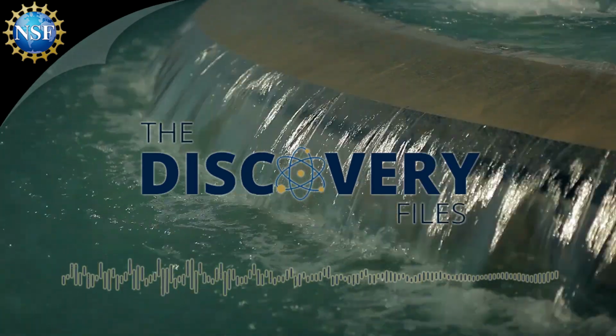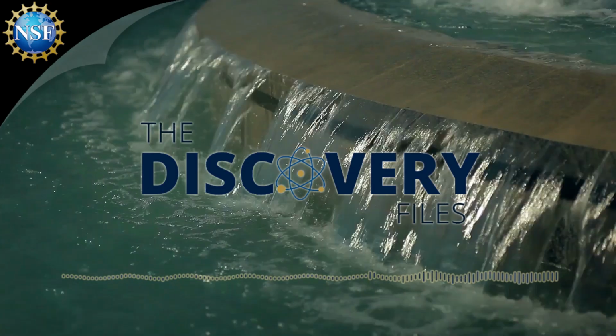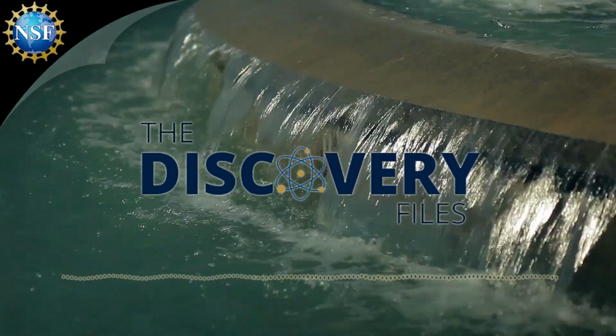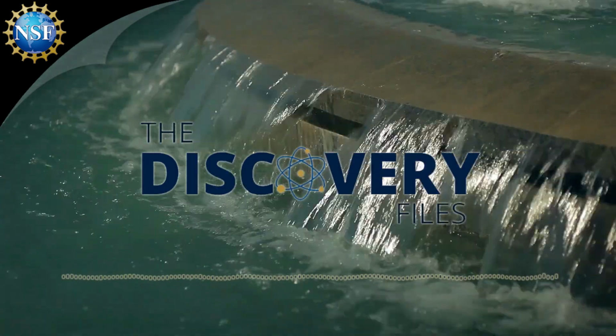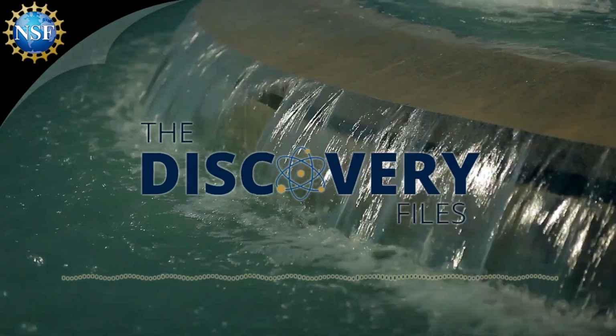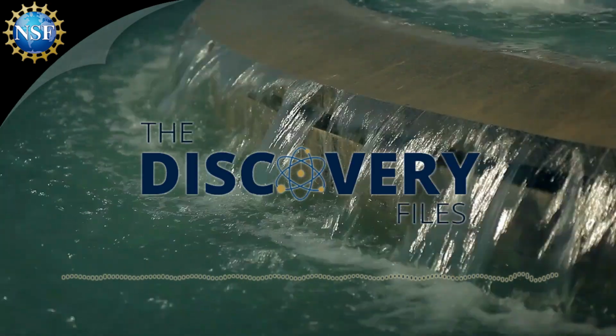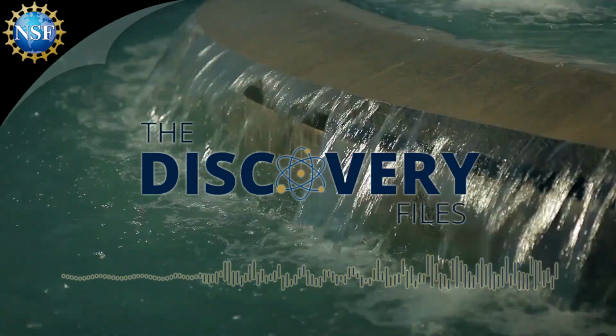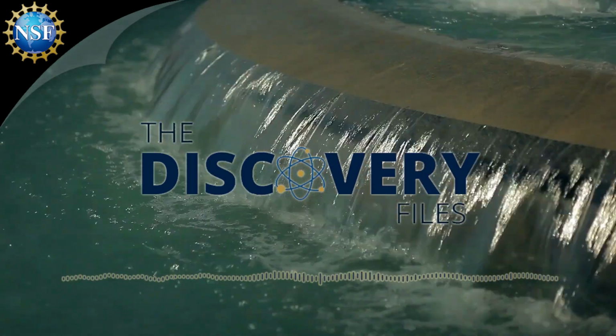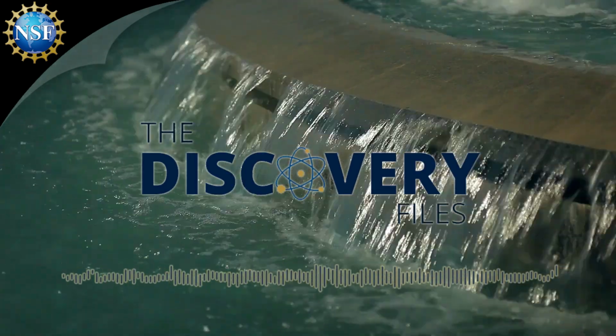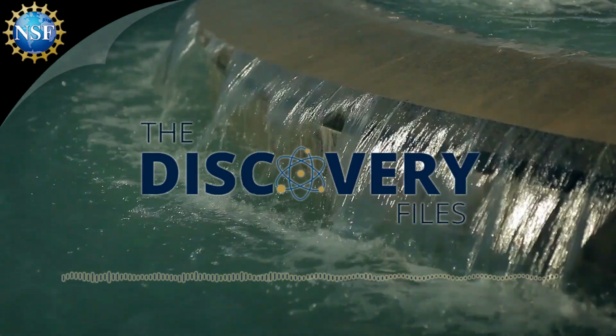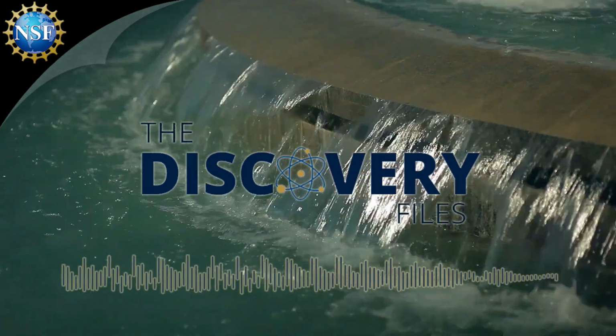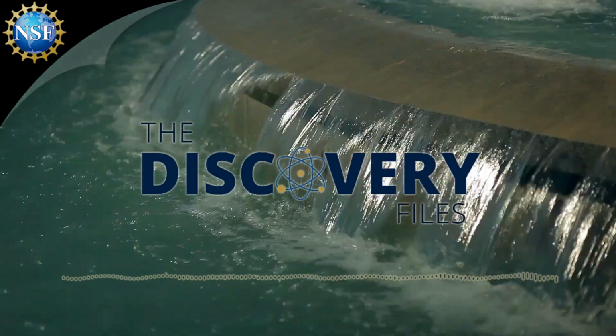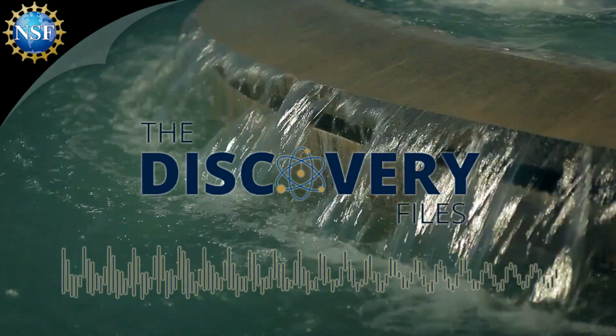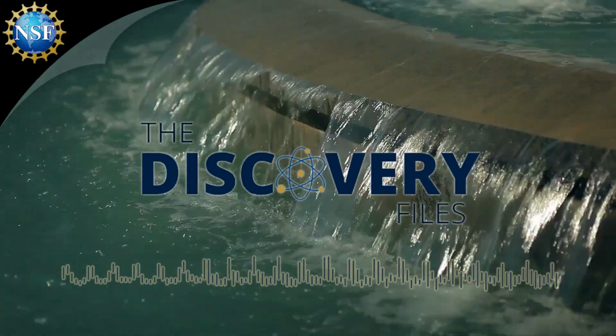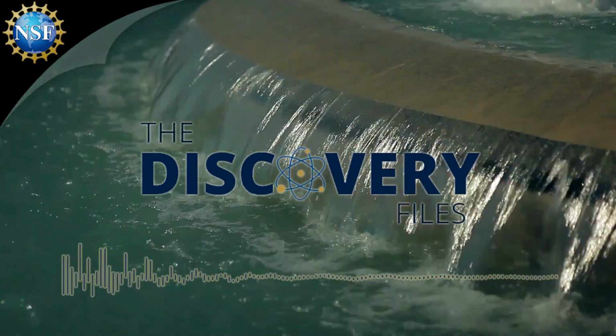Another interesting result was the ability to filter out nano and microplastics, which has become quite a hot topic of late. How did that part of this study work? That's a great question. How did we test? First, we got some nanoplastics. They were 147 nanometer and 400 nanometer polystyrene nanoparticles. And we created a solution, and we passed this solution through the graphene and carbon fiber aerogel. And as a result, 99.99% of these nano and microplastics were trapped on the surface of the graphene